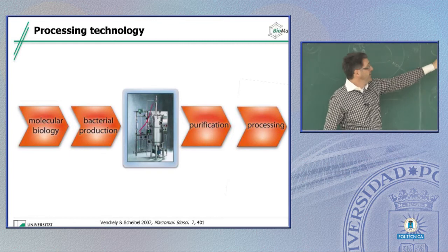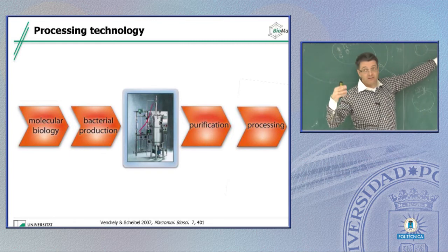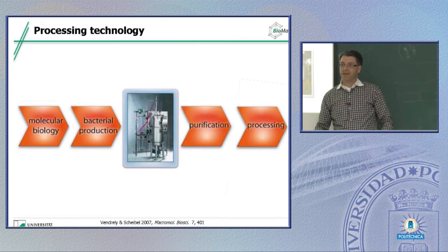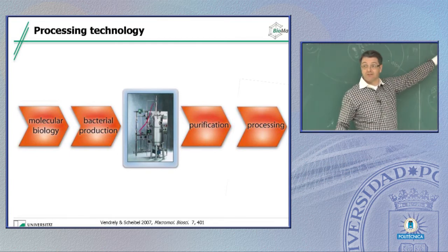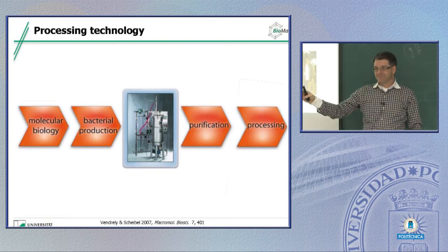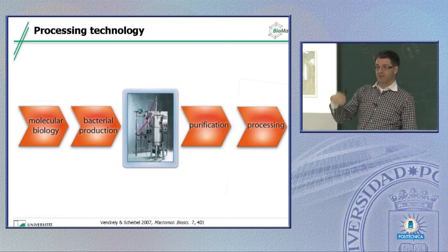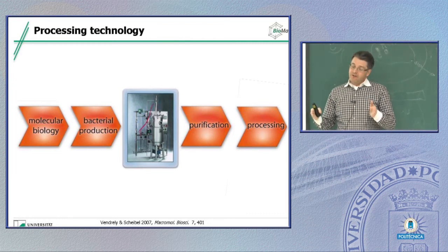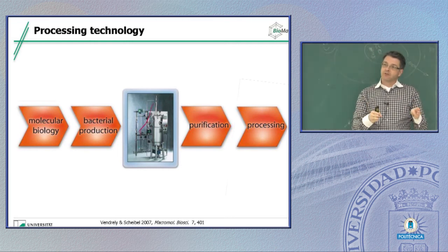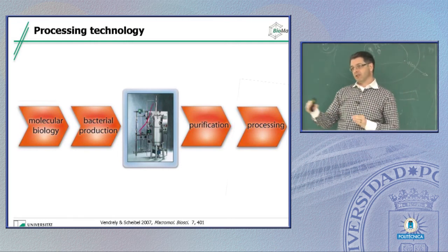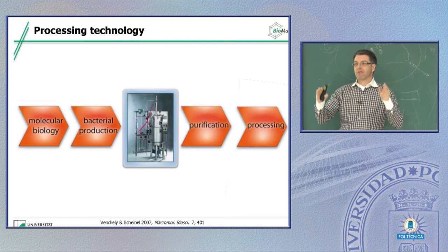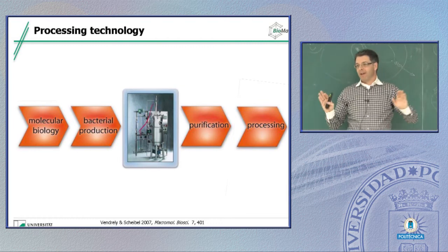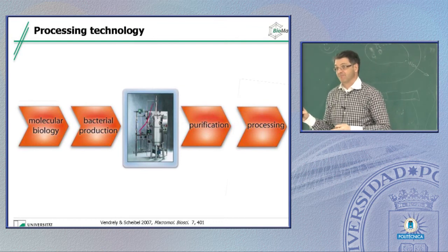It's just in the 0.01% weight per weight. It's very low concentrated, but it's enough. If you induce that to an animal, it will get an inflammation or an immune response or whatsoever. So for medical application, this does not work. Therefore, you have to go to good manufacturing procedures, GMP production. So you have to do everything in a clean room. You have to remove the sugars, which makes the whole thing much more expensive.